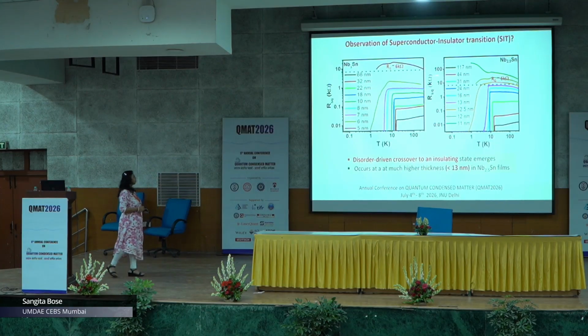So, this is what we wanted to study, whether we can see an SIT in this system. So, we plotted the square resistance, or the sheet resistance, versus the temperature, plotted in the log scale for films of different thicknesses. And what we noticed for the stoichiometric films is that we go from the superconductor to, of course, when we cross the quantum resistance, an insulating phase, but it starts dropping down beyond that. We could not measure lower than 1 Kelvin. So, of course, we can see that there is some downward trend over here.